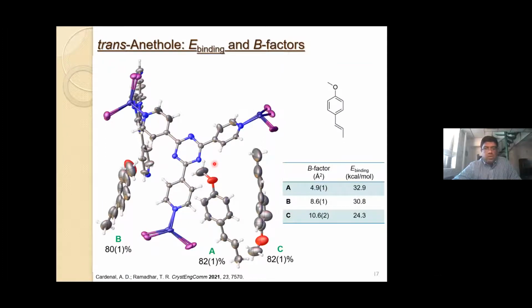And the next thing we wanted to do was to determine the binding energy values for the target molecules inside of the framework. And so here's the asymmetric unit, the experimental asymmetric unit for the inclusion of trans-anethole. You have these three molecules here. I labeled them here as A, B, and C. Below them are the occupancies. And we were able to calculate the E binding values, the binding energies. And in this convention, the higher the binding energy is, the tighter binder it's going to be. Low binding energies indicate weak binding. And so we saw that molecule A here has the highest binding energy.